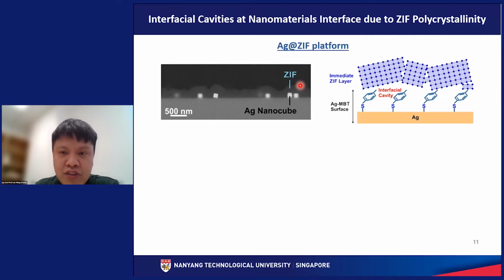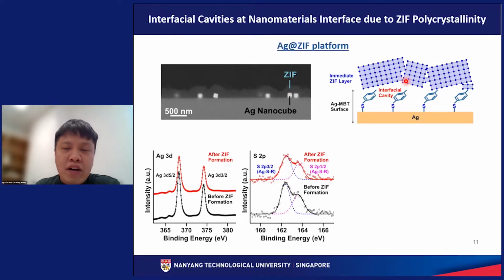Okay, due to the polycrystalline nature of our metal organic framework, we expect the formation of interfacial cavity between the silver as well as the ZIF layer. So this is due to the presence of the methyl benzene thiolate monolayer over here, as well as the polycrystallinity of our metal organic framework. So again, we affirm the formation of interfacial cavity through XPS characterization.